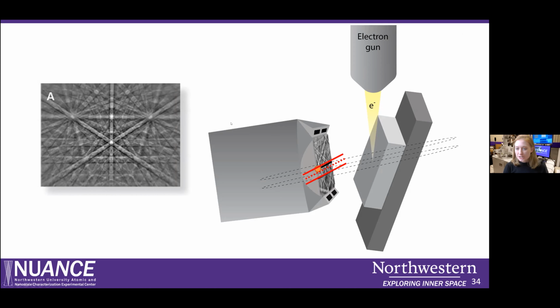The middle line is the one we're interested in, and there are usually 2 darker lines on the top and the bottom from the diffraction cones. And Paul, if you could click again, those lines are called Kikuchi lines and form this Kikuchi pattern. And so the symmetry of the crystal lattice is reflected in these patterns, but how do you analyze this?